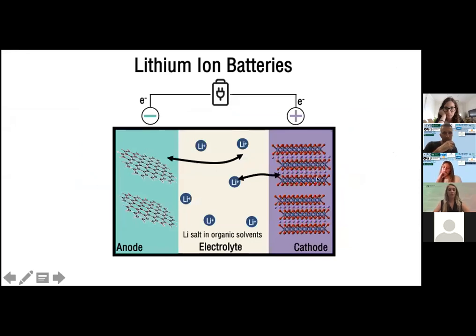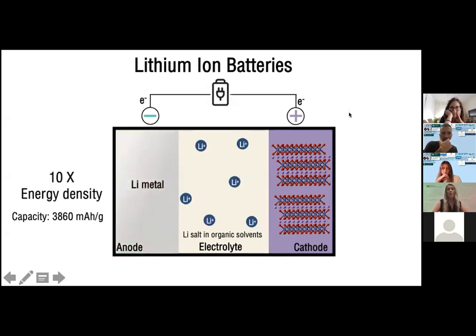The lithium ions shuttle back and forth in the liquid electrolyte, releasing electrons to the circuit and powering your device. Currently, the anode that's used is based on graphite, which has limited capacity. In order to increase the energy density in the cell, one of the most efficient ways to do that today is to switch to lithium metal anode, which stores 10 times more lithium than graphite. However, lithium metal has some problems.